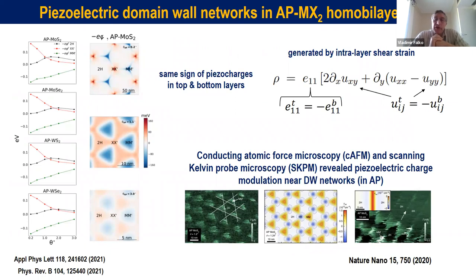When you have deformations in each of the two layers, and these deformations are inhomogeneous, they produce piezoelectric charges. This is because the materials we talk about don't have inversion symmetry, and also because there is charge transfer between the atoms, because it's not purely covalent bonding in the crystal. There is a bit of polar coupling in the materials. And as a result, we have charges that get accumulated around the domain walls in each of the two layers.